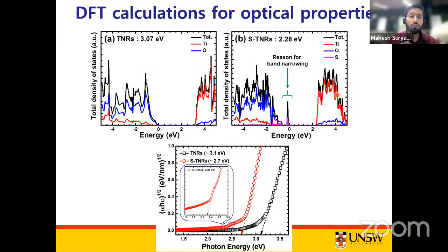So to shed light in detail on the improved performance, we have carried out the electronic band structure calculation of the TiO2 and the sulfur-doped TiO2. And we found some interesting results. The calculated density of states plots, that is DOS plots, of the pure TiO2 yielded a band gap of about 3.07 electron volt, which is close to its theoretical value of about 3.1 electron volt.